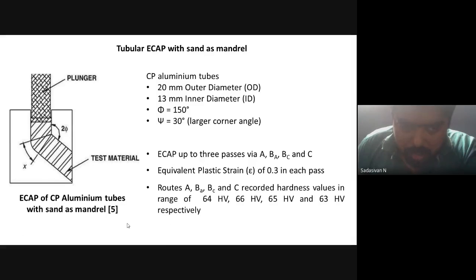I'm restricting my discussion to the process methods and a few accompanying mechanical properties. I'm not going into microstructure. These routes were followed, and route BA was found to give the highest amount of hardness, though it was quite comparable, not much of a difference between processing routes. Processing was carried out only up to 3 passes. So this is one method to perform hollow ECAP.